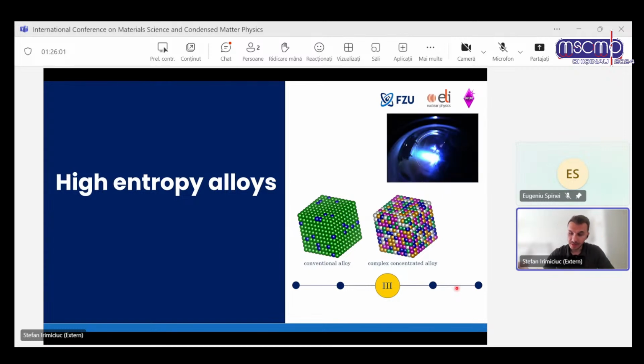But the fact that it's complicated, and the fact that it has all these tweaks and high acceleration and energy in the plasma. And if I move past it, because maybe, but we can talk about it later. The energies for the ions in the plasma are reaching hundreds of electron volts, and in some cases even kilo electron volts. So in terms of energy, it's a high energy plasma.